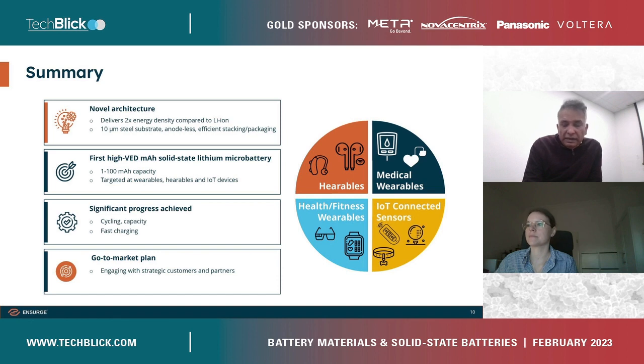There are other cathodes one can use for higher energy densities to operate at higher voltages, but these also come with higher impedances. The core factor that determines its use in a product is basically the ability to discharge the battery at a high rate, especially in the pulse for communications. So we don't want the impedances to go high. We prefer to be going to 4.2 volts, maintaining the long cycle life, and still operating with very high energy densities in the small form factor.